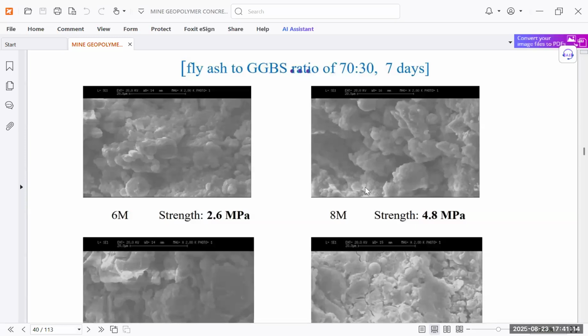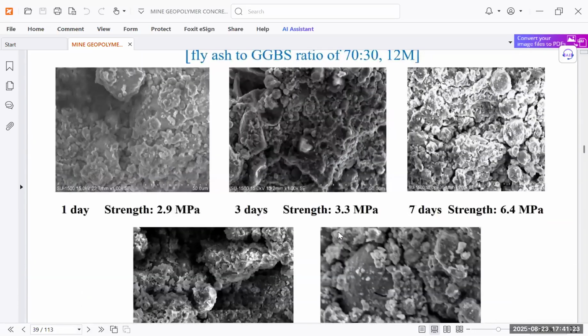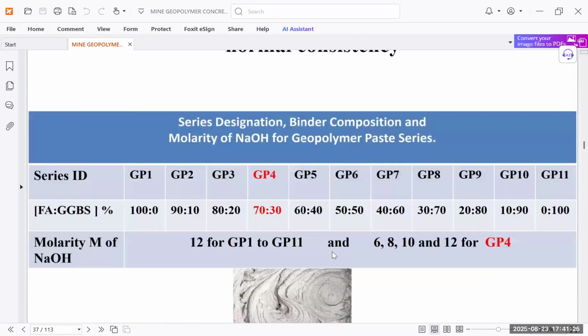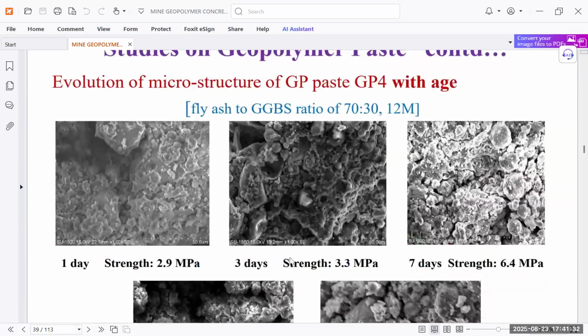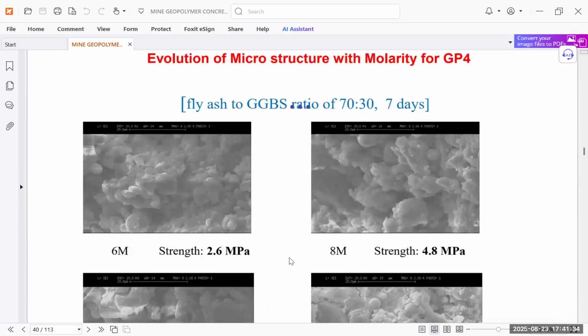You can see our strength is varying with the molarity. The fly ash to GGBS ratio is the same, 70 to 30, and it is 7 days strength, but with molarity the strength is changing. That is why we have changed the molarity also in this case. You can see 6, 8, 10, 12 for GP4 and 12 for GP1 to GP11. That is why our molarity is also affecting the 3 days strength or 7 days strength we can see.